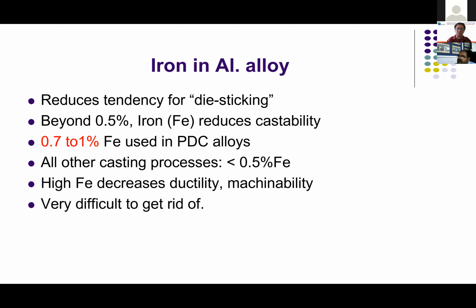There are some castings, especially wheels, which are made in gravity die casting, GDC process, and here we maintain GDC 70%, 30% by LPDC. Here we maintain iron less than 0.1 because the more the iron, your elongation goes down. The safety critical components like brake parts or wheels should have a very good elongation. This is very important, very critical.